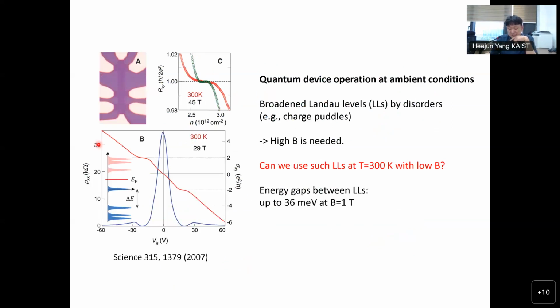And Landau levels happen if we apply high magnetic fields. But if we apply 1 Tesla, for example, this is also a high magnetic field. The energy gap between two Landau levels would be something like 30 milli eV. But we can never observe Landau levels at room temperature at 1 Tesla. So to see Landau levels or quantum Hall effect at room temperature, we need 30 Tesla, which is quite challenging in our laboratory, in your laboratory.